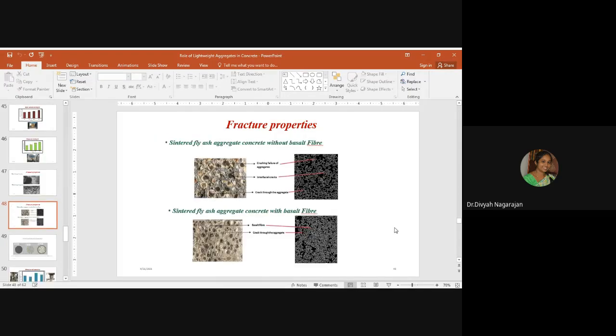Here I have elaborated the fracture properties using MATLAB image processing. I have image processed the cut section of the specimen using MATLAB software to study in detail. It can be seen that the crushing failure of the aggregates, interfacial cracks, and cracks through aggregates were observed without basalt fiber in sintered fly ash aggregate concrete.